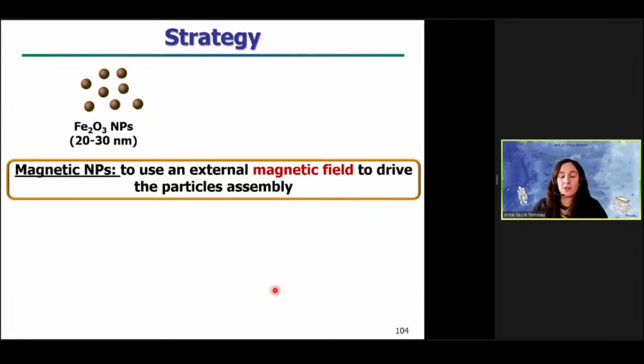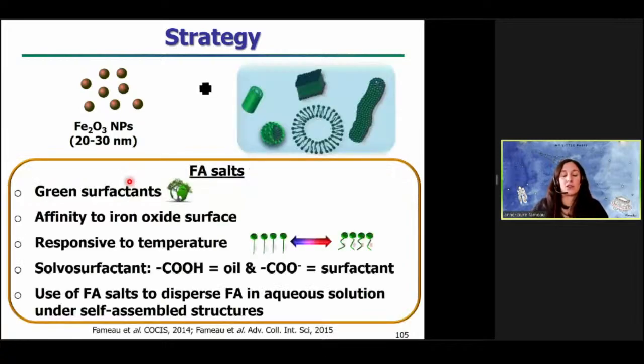So our strategy to achieve this aim was to use iron oxide nanoparticles, maghemite nanoparticles with a diameter around 20-30 nanometers. Why magnetic particles? Because we wanted to use an external magnetic field to drive the particles assembly. And then it was just to disperse these nanoparticles inside the fatty acid soaps aqueous solution based on fatty acid assembly. Why again fatty acid soaps?